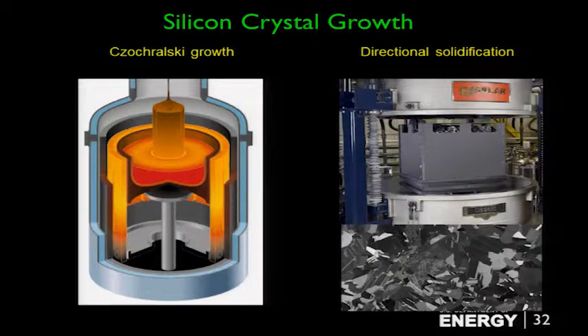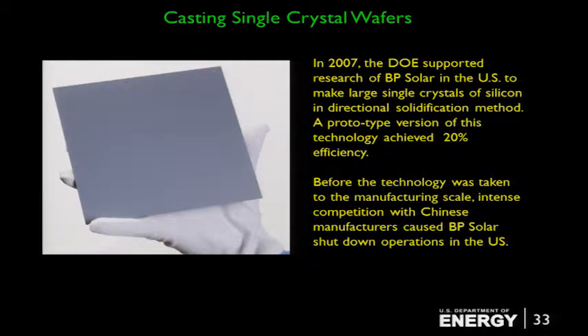Now, the comparison between single crystal and polycrystalline is like night and day in terms of the cost. And in the right-hand solution, you have this big bulk. That's a sample polycrystalline. They're grown in vats this big, melted and purified, and you get these polycrystallines. But if you cool and anneal very, very carefully, you can get directional solidification, and you can get a half, two-thirds of that polysilicon actually to be single crystal. And so this is something, again, the Department of Energy supported, BP Solar in the United States. That's a sample of some of the directional solidification that made a silicon cell that had 20% efficiency. As you know, within 1 or 2% of the best commercial grade stuff, non-space commercial grade stuff.